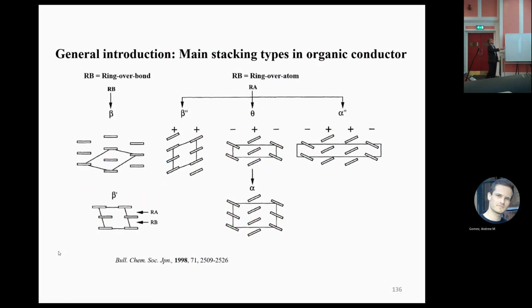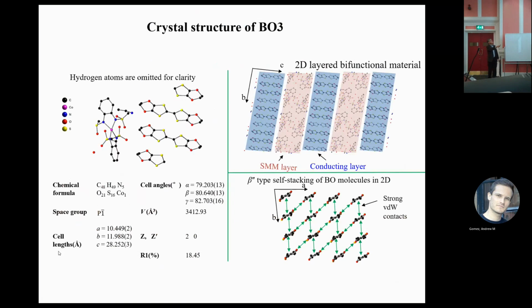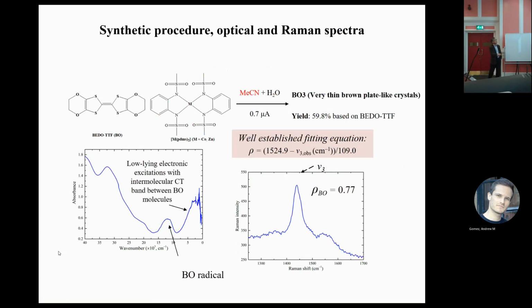So beta double prime BEDO-TTF is this kind of stacking. So this is a crystal structure. This is organic BEDO-TTF. This is a single molecule magnet. So segregated two-dimensional stackings are observed. So from the Raman spectrum, 0.77. So partial charge transfer occurs from the donor to the acceptor. So this is the evidence for a conducting single molecule magnet.